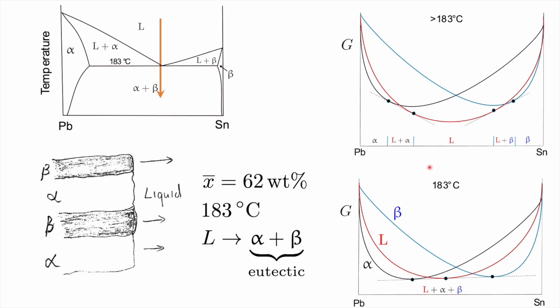Now, in terms of free energy diagrams, let's consider the cooling of a composition here, which is the eutectic composition, from high temperatures. At high temperatures, that eutectic composition, which falls somewhere here, would only have the liquid phase stable. These common tangents here represent the liquid plus beta and the liquid plus alpha phase fields. But our composition is here, and that composition would give us simply liquid at a temperature above 183 degrees centigrade. But at 183 degrees centigrade, the liquid is able to decompose simultaneously into alpha and beta here. The three phases have a common tangent, and therefore they are all in equilibrium at the eutectic temperature.